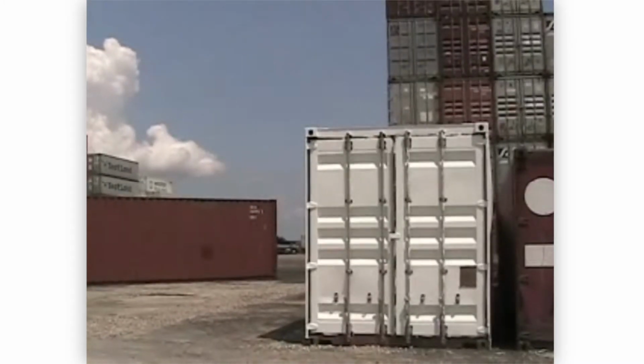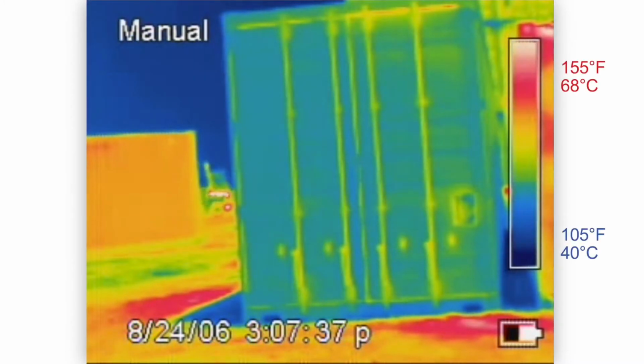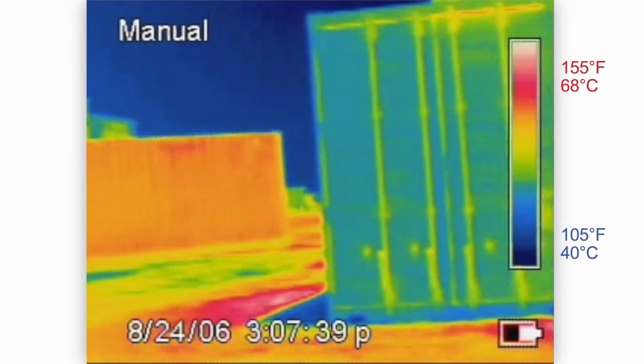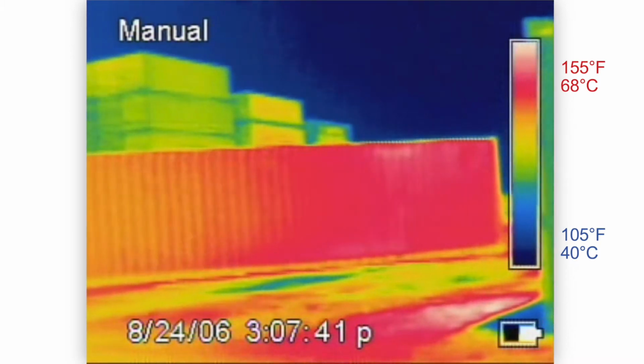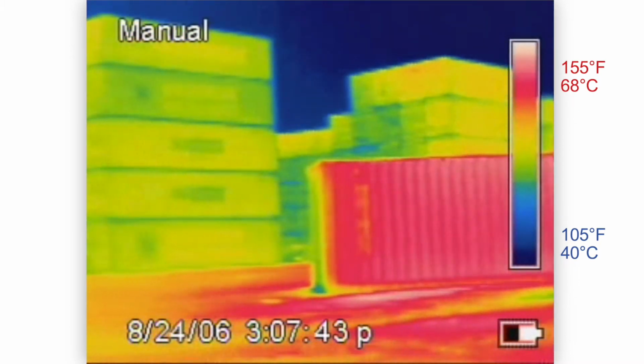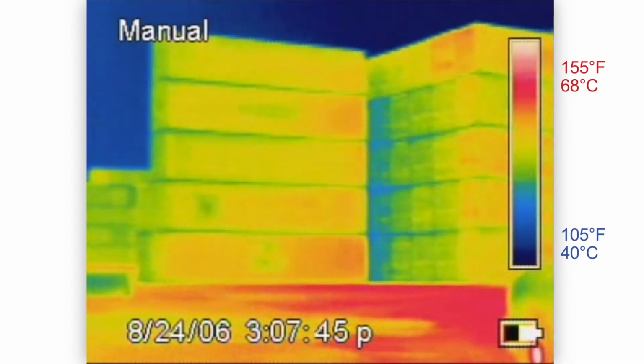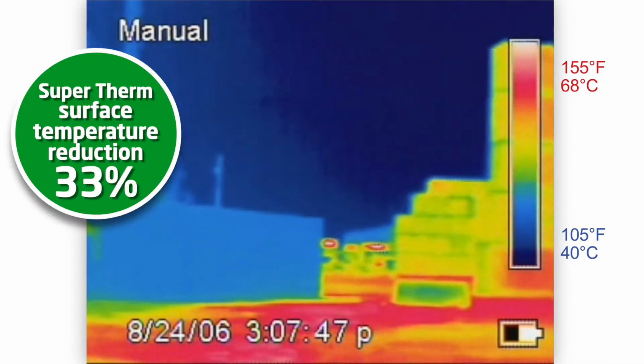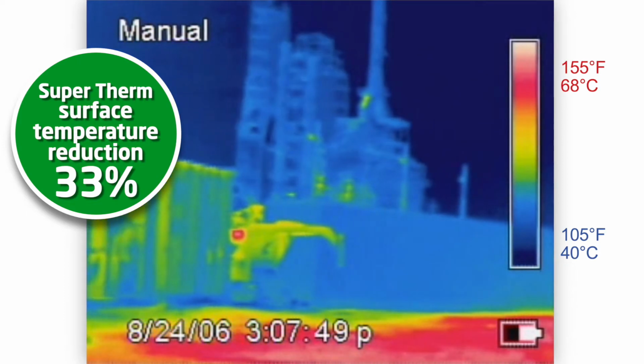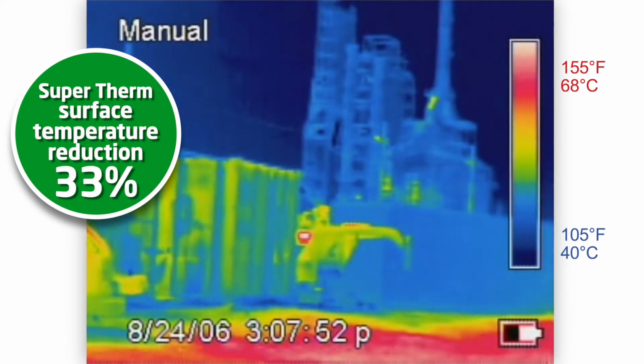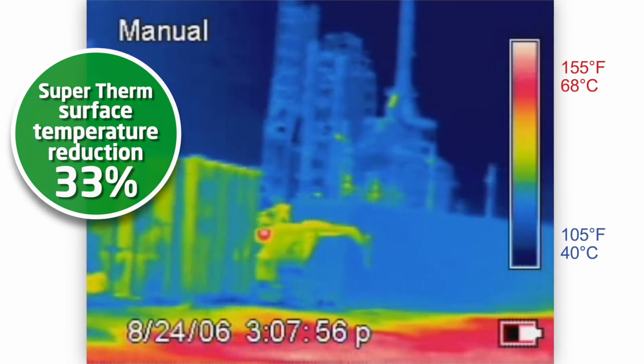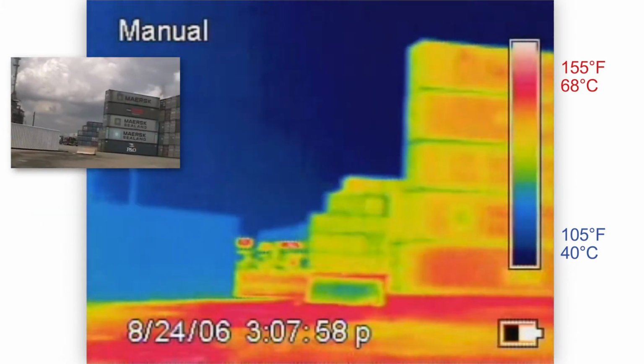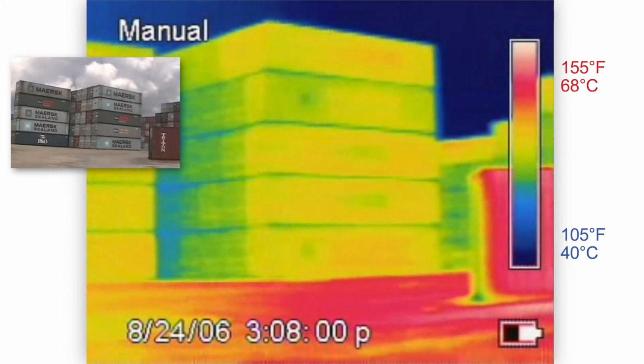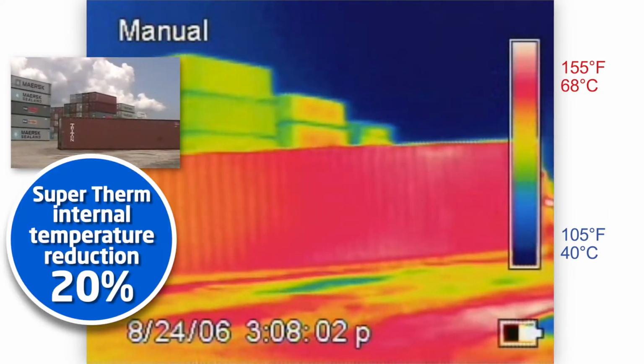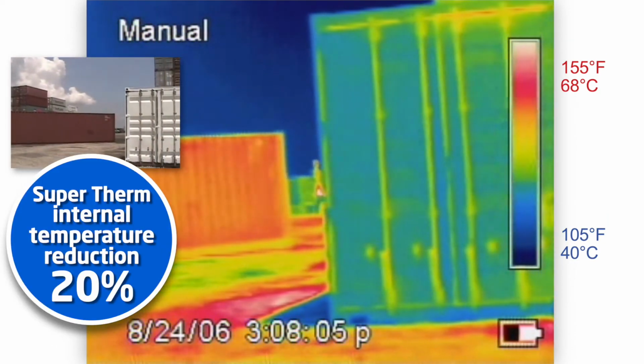As you will see in the thermograms, the darker areas indicate cooler temperatures, while the higher color and white areas indicate excessive heat. The Super Therm product effectively reduced these thermal gains from as high as 155 degrees down to surface temperatures that were manageable at 105 degrees. The corresponding internal container temperatures were also reduced from a high of 118 degrees down to 95 degrees.